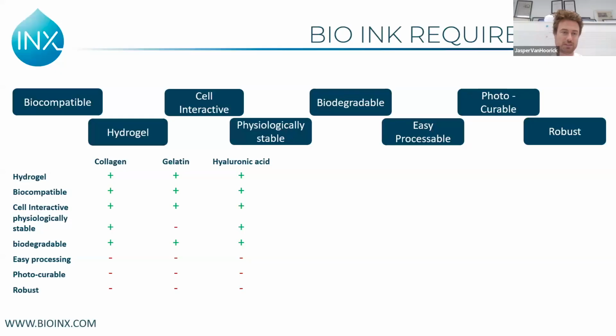If we look at these materials and we add the properties there, we see that all three of them are hydrogels, they're biocompatible, they are cell interactive. Collagen and hyaluronic acid are physiologically stable. Gelatin is not because it dissolves at 37 degrees, well, even at 30 degrees. And they are biodegradable, so biologically they are doing quite well, but printing-wise, they are not, because they're very difficult to process, they're not photocurable, and they're far from robust. So we need to find other materials.